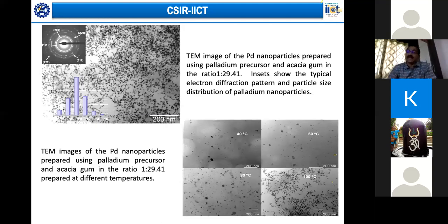And when I did this, because as I said, I am into characterization, and when I do all these things myself, I got very excited to see that all these particles are of uniform size and they are dispersed all through the grid. Wherever I could see the grid, they are very nicely dispersed, and the size most of the time is between 8 to 10 nanometers. And when these particles are of uniform size, especially palladium less than 10 nanometers, it is a wonderful catalyst for many of the organic reactions.